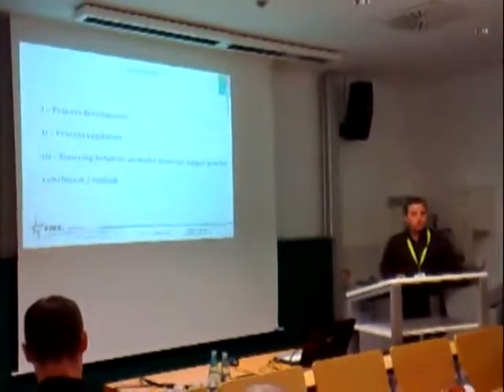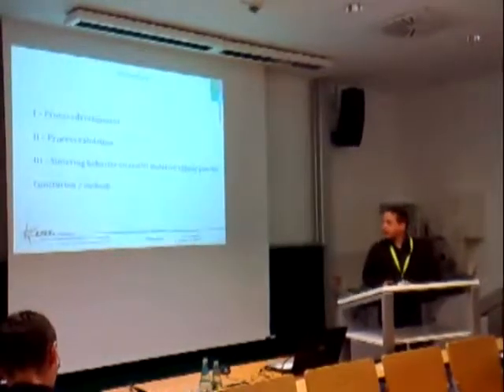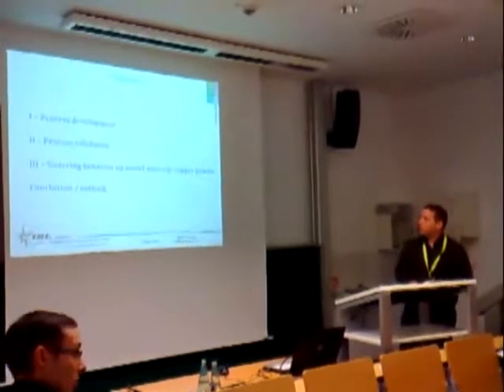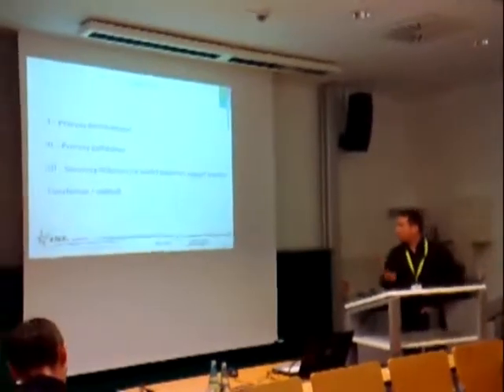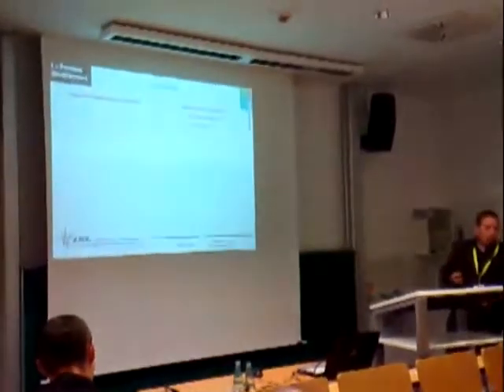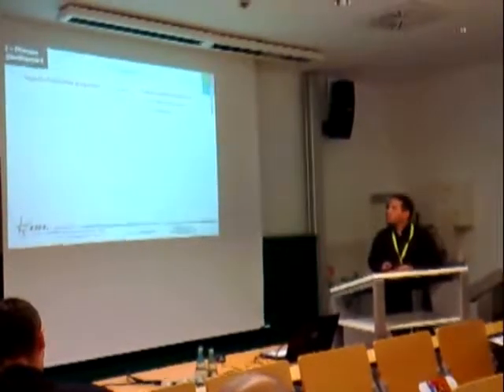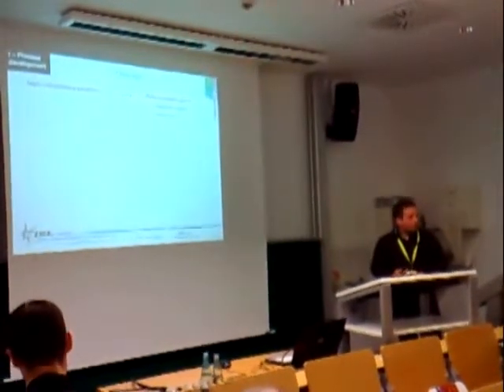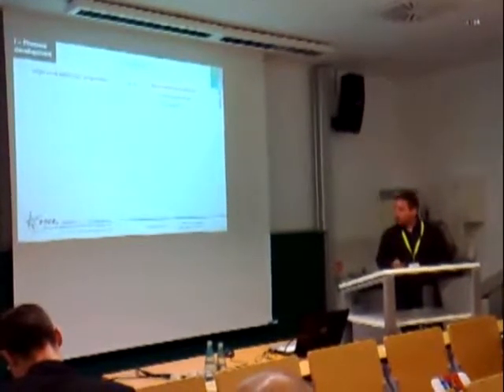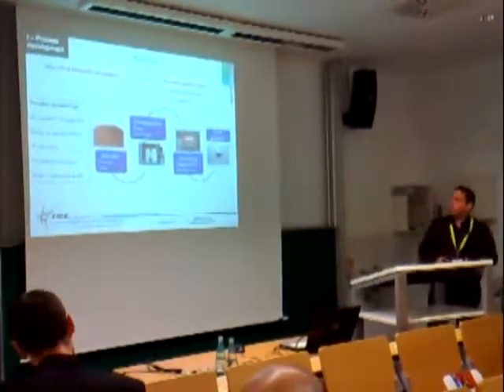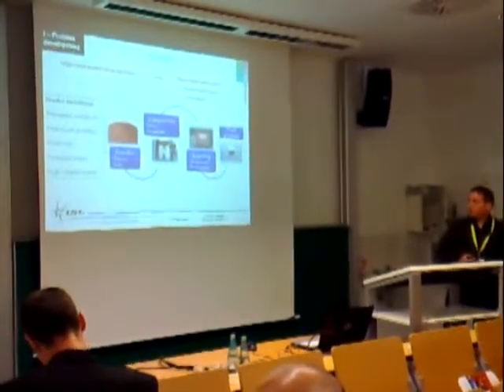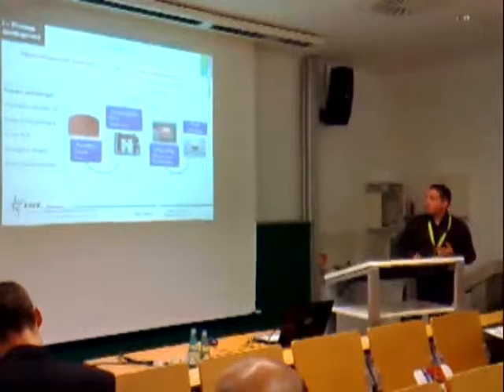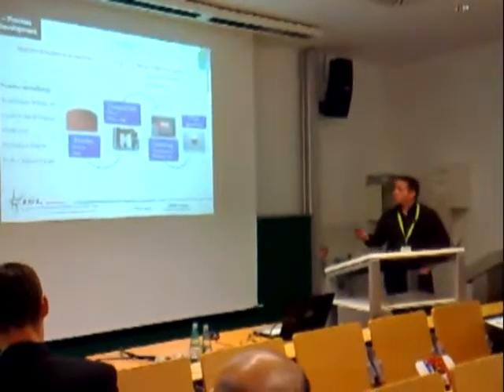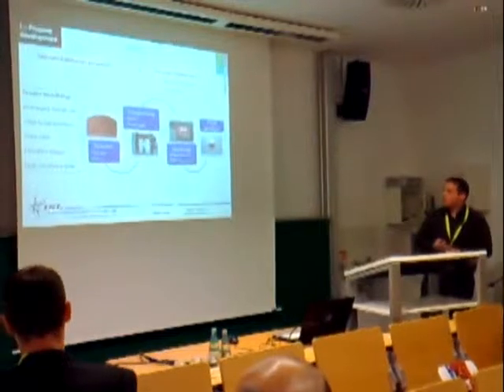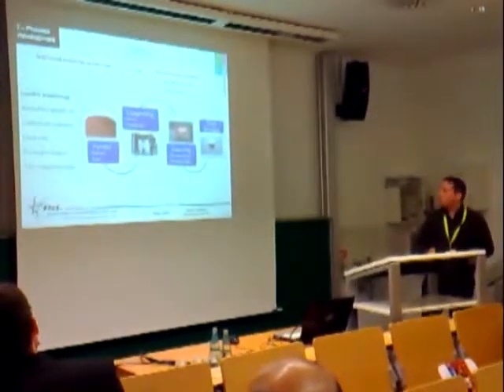In my talk, I will first present the process and the process validation, and then we will have a quick look at the sintering behavior on a model material, which is the first topic for the panel we conclude. To get material with improved properties, one way is to have microstructure control, either by nanostructuration or texturation. So we have chosen the powder metallurgy route because you can sinter virtually all materials and you can have millimeter to nanometric powders. After choosing the powder, generally you have a compaction step followed by a sintering step and you get your final product.